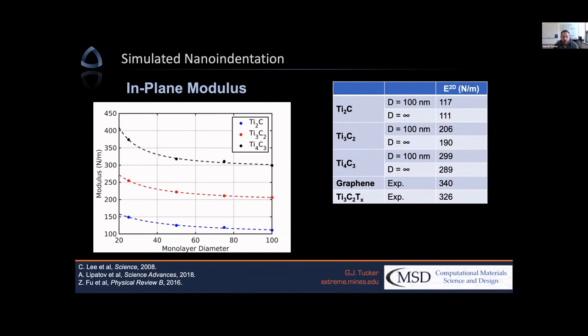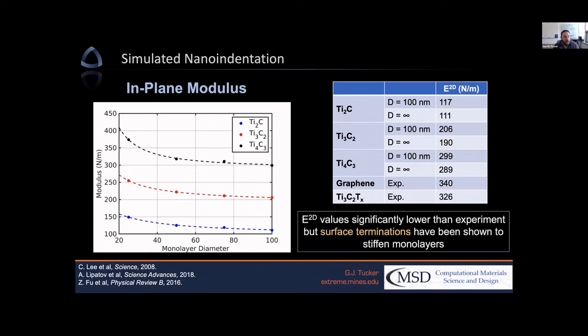So from that data, we can actually then also output the in-plane modulus. And so shown on the left here is the modulus versus the monolayer diameter. And as you increase the monolayer diameter from tens of nanometers up into 100 and beyond, what we start to see is we approach values for that in-plane modulus for all three systems. And shown on the right is a table comparing the calculated 2D modulus value for the three different systems, both at the 100 nanometer size that we simulated, in addition to the functional fit as you increase the diameter out to infinity. And we compare these to both the experimentally measured values of graphene and Ti3C2 with termination groups. And what you can see here, obviously, is that the in-plane modulus values are significantly lower than experiment, but we know that those surface terminations have been shown to stiffen the monolayers. So we have to think about that too.